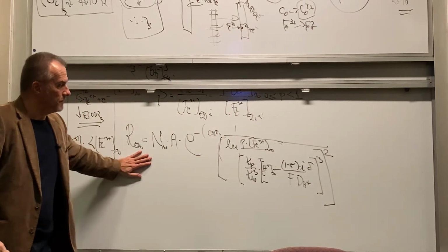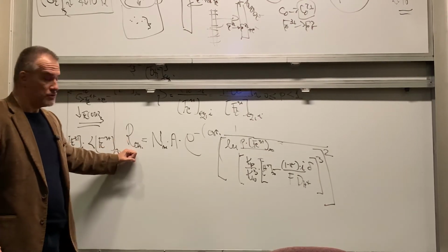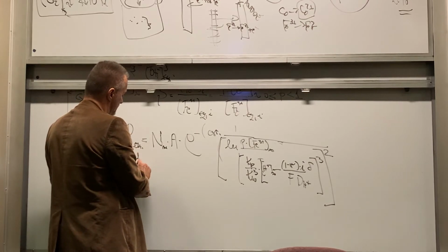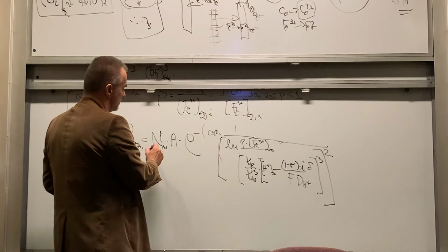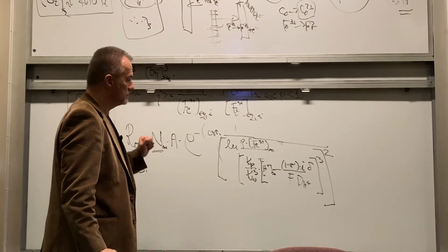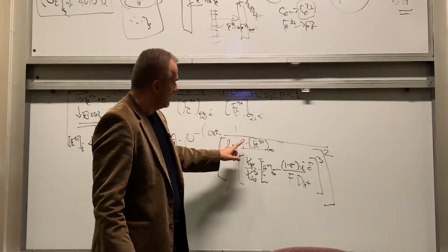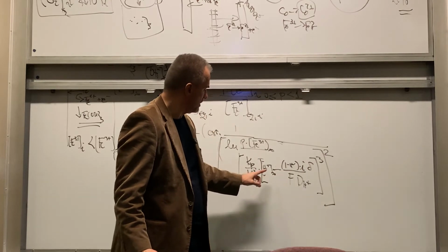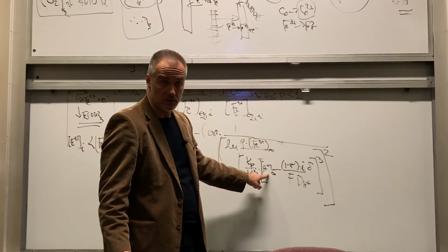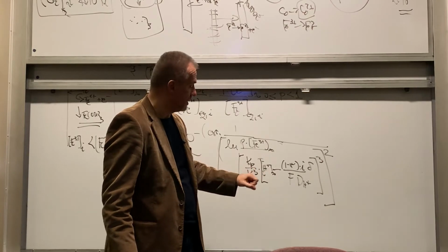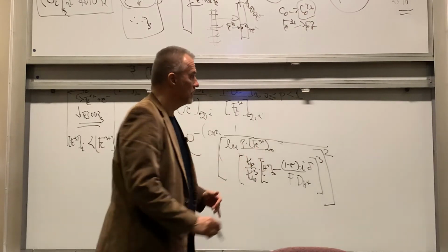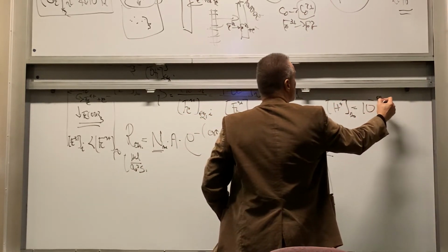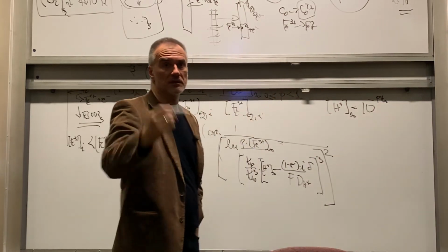So now I have an expression for hydroxide rate incorporation in moles per centimeter square in second, and this is basically some constant, we don't know what it is, and then it will be a function of the process parameter current density, diffusion layer thickness, concentration H plus in the bulk, which you can write as 10 to the minus pH. So H plus in the bulk is equal to 10 to the minus pH of the bulk. You know that pH is the negative logarithm and so on.